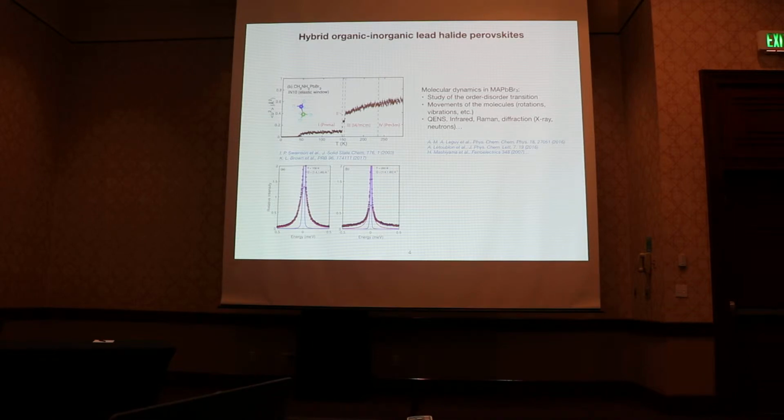There have also been many studies, in particular with Raman and infrared spectroscopy, which allow us to identify the many rotations, movements, and vibrations of the molecule in its disordered state. And also it has been shown that although the molecule doesn't directly affect the electronic band structure, its coupling to the inorganic framework through acoustic phonons can affect the mobility and the lifetime of charge carriers, and also the thermal transport.